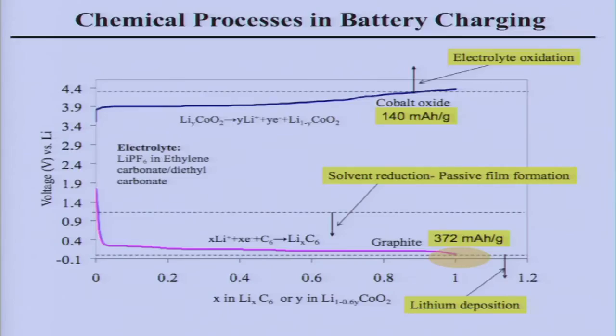If you look at the detailed operation of the batteries, what happens when you plug in your cell phone or laptop onto the wall? This is the process happening. This is the voltage versus lithium. This is your negative electrode, that's graphite, measuring its potential versus the amount of lithium you put in during charging. This is the process of lithium cobalt oxide. When you put lithium and electrons in, or take lithium and electrons out, its voltage goes up. Negative electrode voltage is going down. Let's look at the negative first.